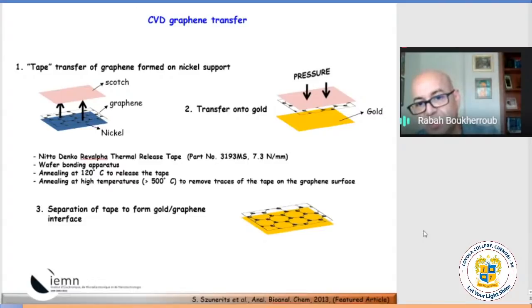So the first technique, I think that's exactly how the Nobel Prize was awarded. It's the Scotch tape. Typically, you buy your graphene on nickel or copper. You apply Scotch tape made out of polymer. You press against the nickel graphene, and then you have a transfer of graphene to the Scotch. You just wait for it to release. It's like a stamp.